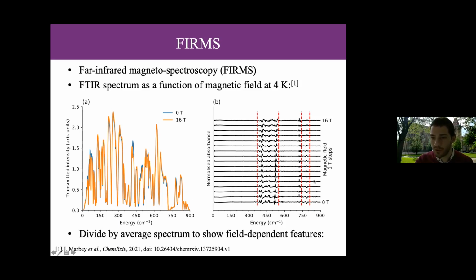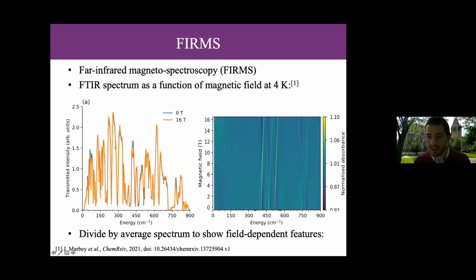And so this is just a few different field steps, but you can see that there are features that are changing as a function of field. So anything that appears here as a squiggle means it is changing as a function of field. Okay, so there's something around 450 plus or minus 100 wave numbers, and then something around 770 or something like that. You can also plot these data as a heat map, and so it starts to look like this.